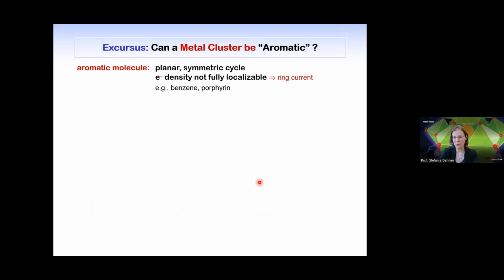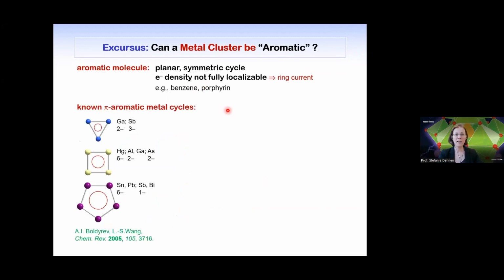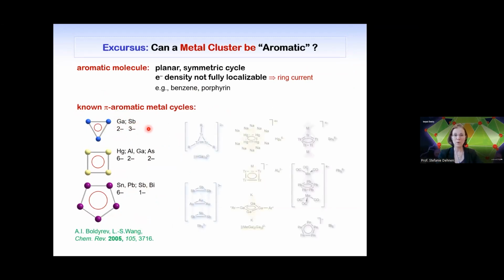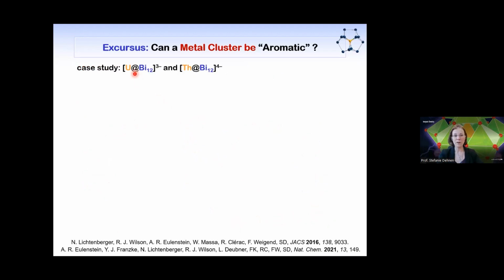And here is a little excursus, because in the course of our chemistry, we asked ourselves more and more whether these metal clusters can be aromatic at all. And here I'll do just a little slip into simple chemistry and talk about something that is connected to multimetallic clusters, because there are known pi aromatic metal cycles, and these are all that have been known so far. So triangular, square type, and pentagonal rings with exactly these elemental combinations and charges. These turned out to be pi aromatic, but all of them have been included in much more complicated clusters or complexes. So they have been shielded and decorated, protected from further decomposition by ligands usually. So our case study is different.